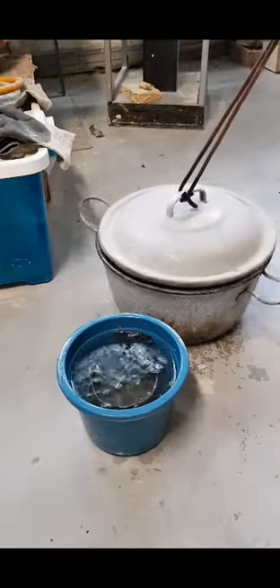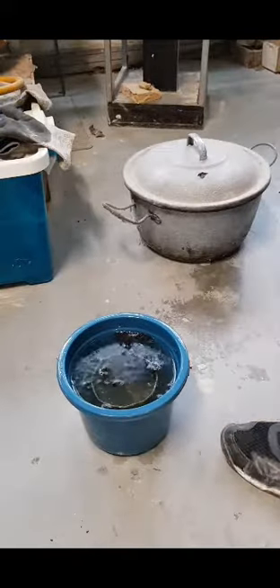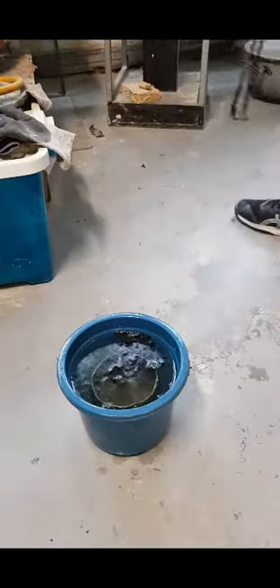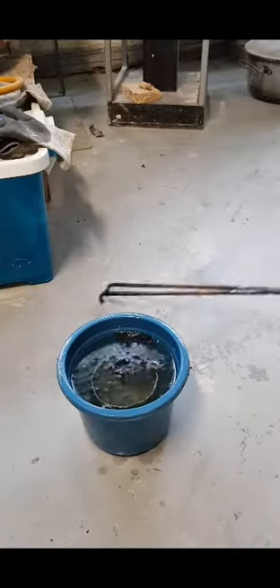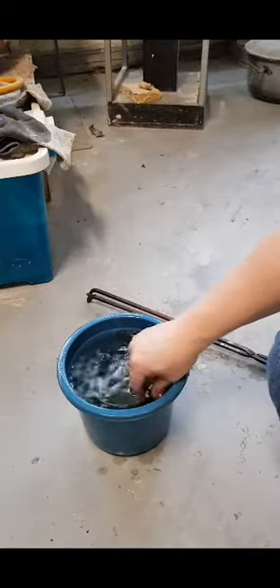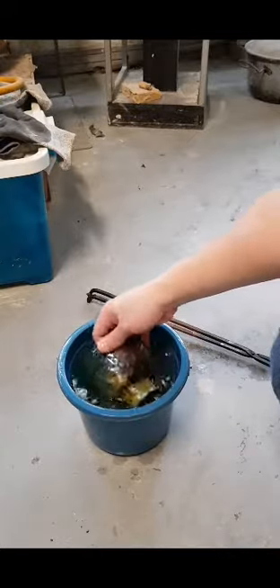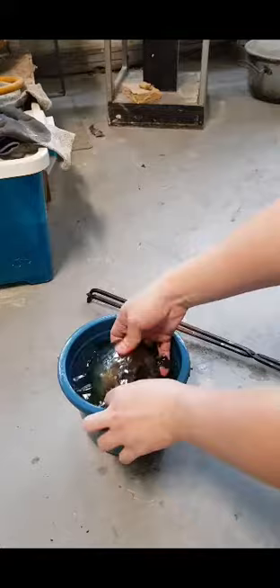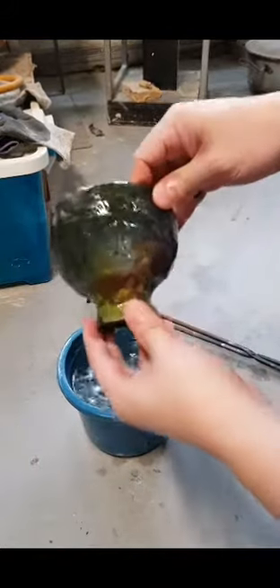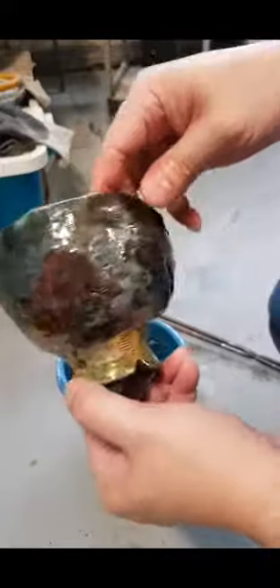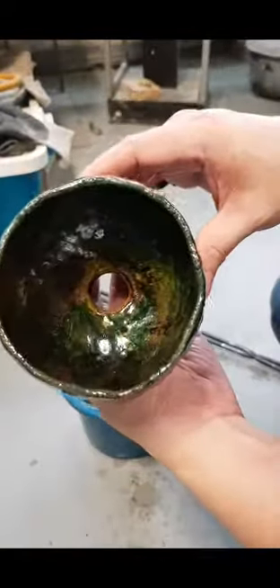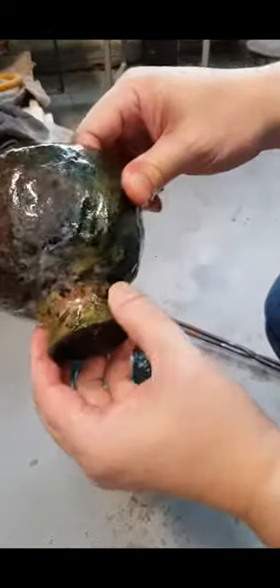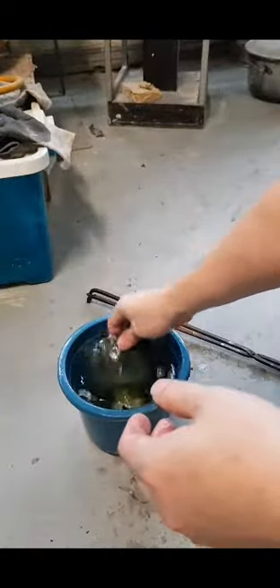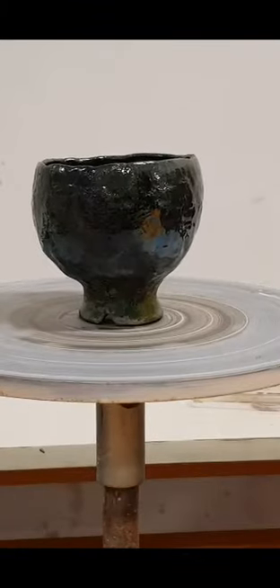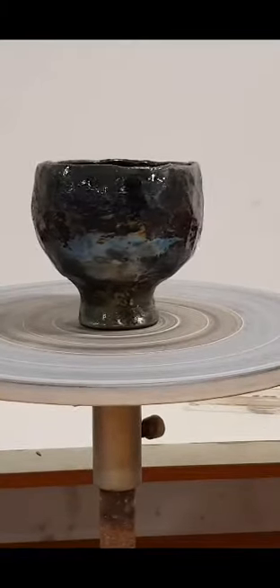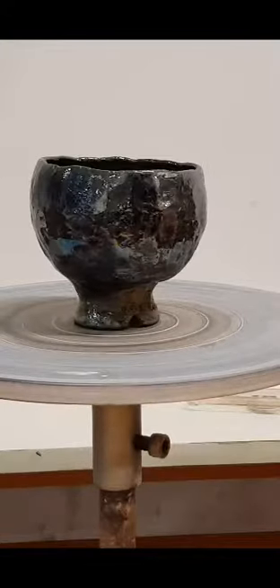And you can start seeing bubbles coming out from the pot. That's because Raku pots are usually very porous, and they contain basically thousands, millions of fine little cracks all around the glaze and the ceramic itself. So you see all that luster that came out from the post-reduction. This is typical with a Raku glaze that has copper oxide. You get green, you get metallic red, you get sometimes golden color, all kinds of combinations like a rainbow.